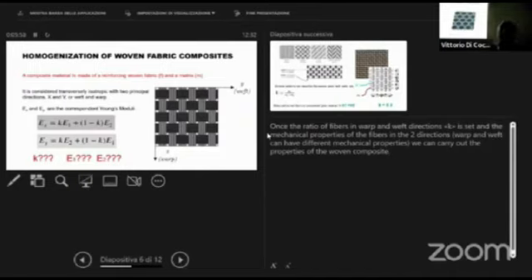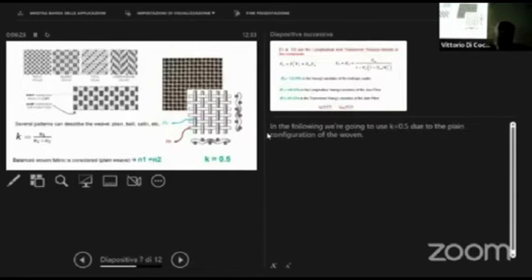We're using these two expressions to obtain the modulus along the weft and along the warp, and we know that in the case of our architecture of the texture, the coefficient K is 0.5 because we have a plain weave texture in which the number of fibers along the warp is equal to the number of fibers along the weft. So we have the same rigidity in both directions. So we set K as 0.5, given the architecture of the fabric, and we have to determine the longitudinal Young's modulus by considering the characteristics of the raw materials.